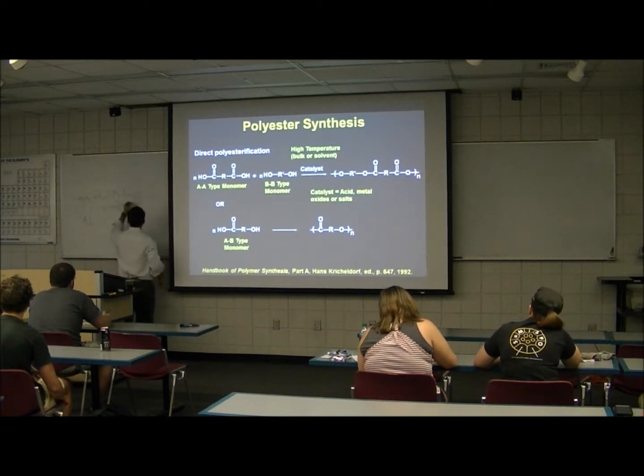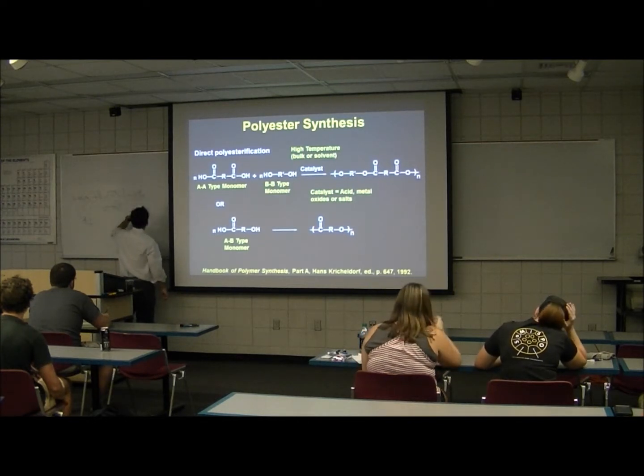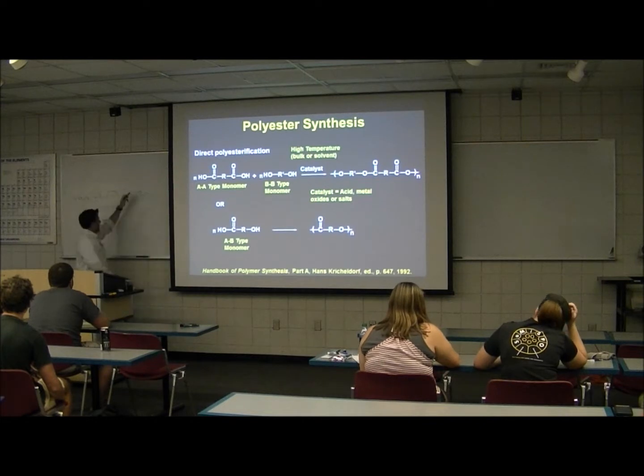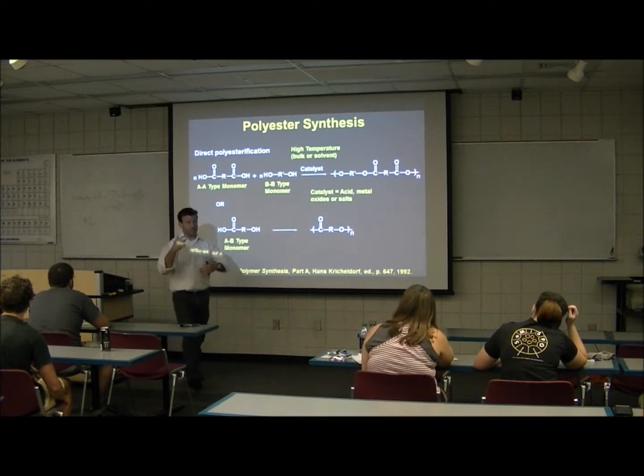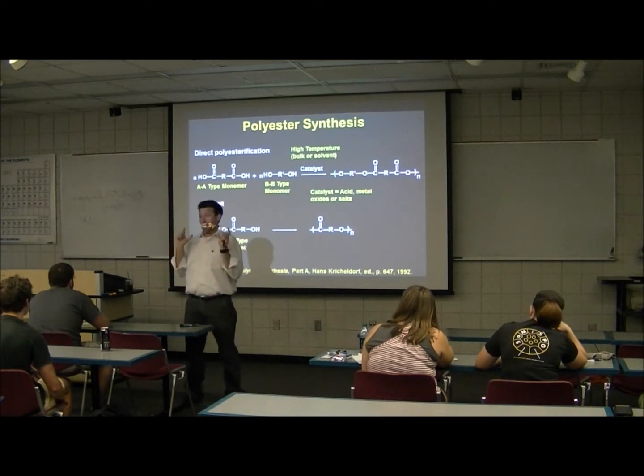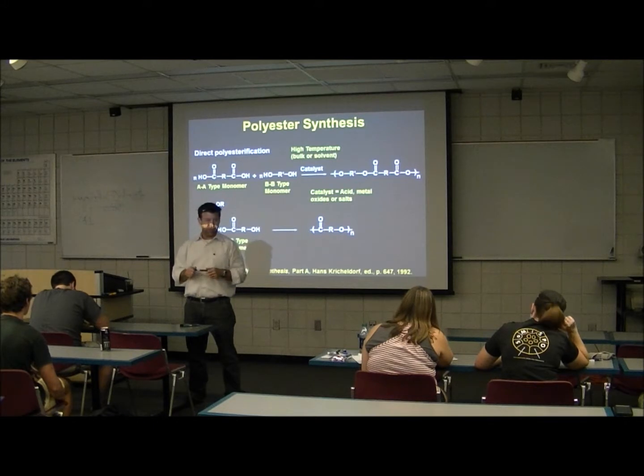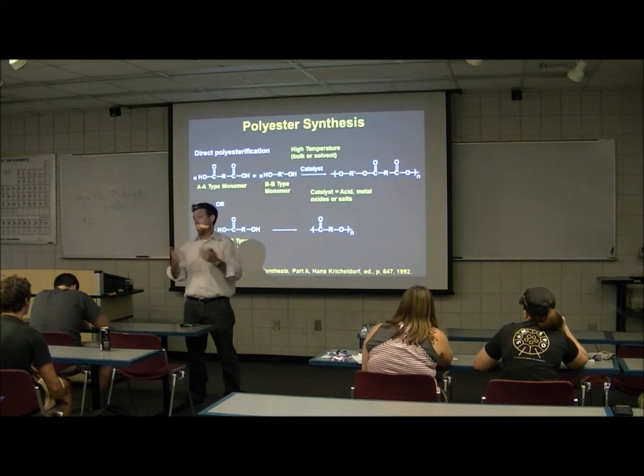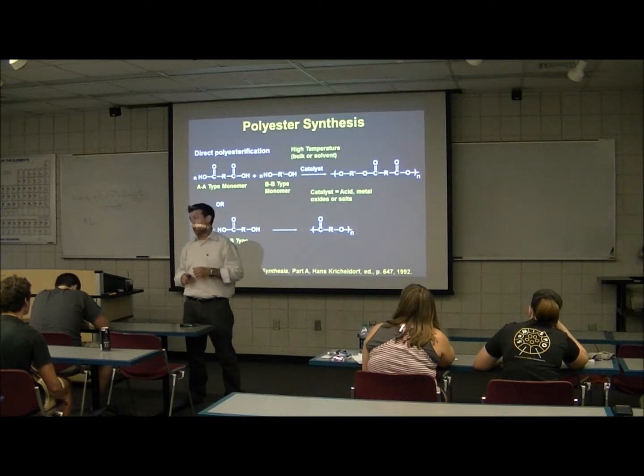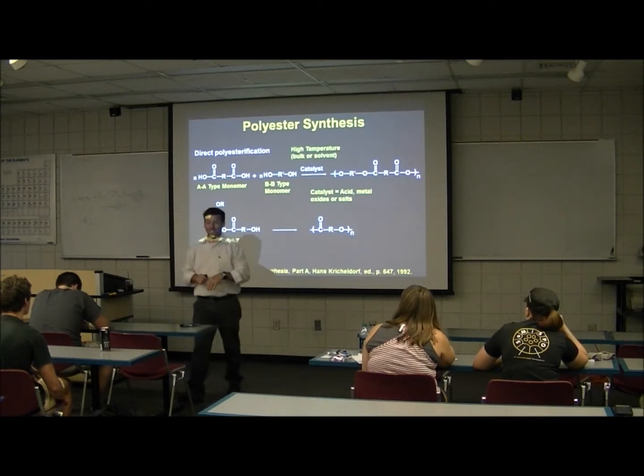you'll see this later, where you've got tin in some form here with terephthalic acid or isophthalic acid. So you put tin oxide and in situ, it rearranges to be the diester of one of the acids. And when that happens, then the tin is soluble. It's soluble in the system. It's not a heterogeneous phase reaction, and the tin has activity. But the tin still doesn't catalyze esterification until you get above about 220 C.